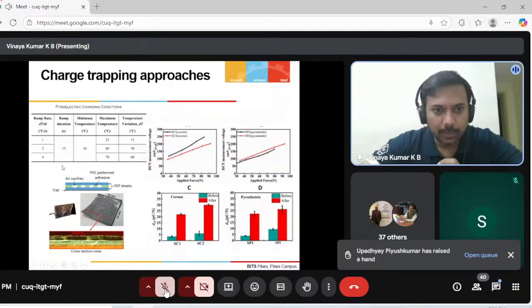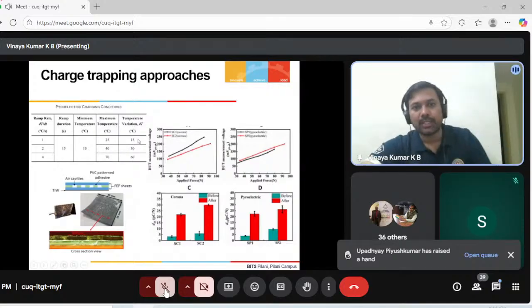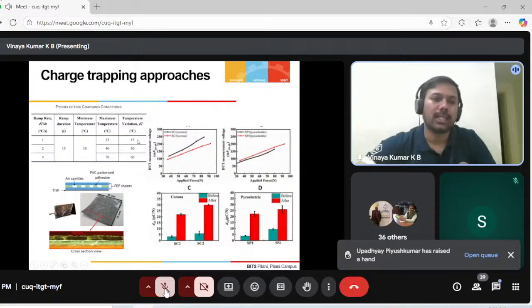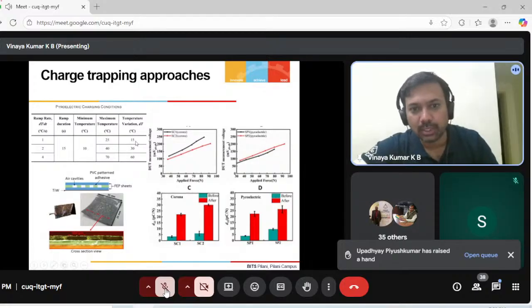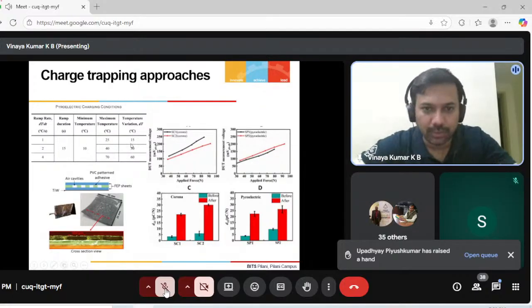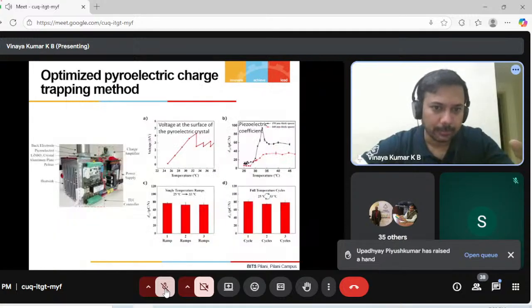And the temperature, as I said, the delta T, the dT by dt we applied, is very low. It's like 15 degrees, the ramp duration 15 seconds, and the minimum temperature is 10 degrees. The maximum temperature we achieved is 25, from 10 to 25, 10 to 40, and 10 to 70. The temperature variation of 15 is still, I would say, very high. Even so, we have results produced with 8 degree and 10 degree temperature variations. So it's a low temperature charge trapping method in the voids on the piezoelectric systems.